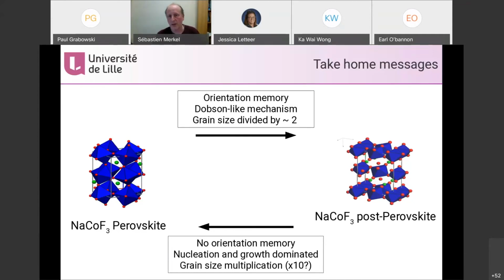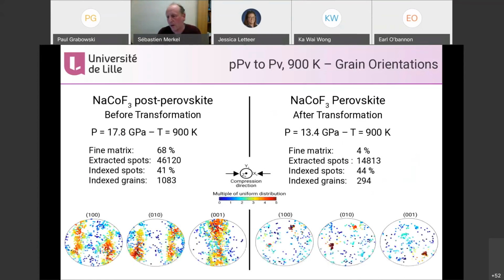And you lose the orientation memory, so you don't have any memory of the orientation before. In the figure here, the crystals of perovskite that we are growing don't have any specific orientation relative to the starting material. It's just one orientation that just started the transformation and then took over, I believe.